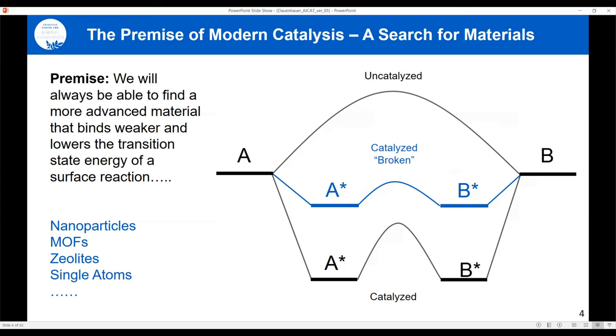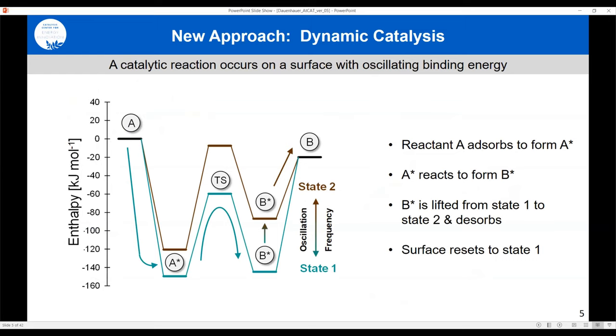We search for materials believing we can take a reaction with a very high uncatalyzed barrier and find a material that drops us to a lower transition state energy. The problem is the desorption energy is so high that we have to balance it with the surface reaction energy. What we want is to both reduce the binding energy and at the same time reduce the transition state energy — breaking the scaling relation — perhaps through nanoparticles, MOFs, zeolites, or single atoms.